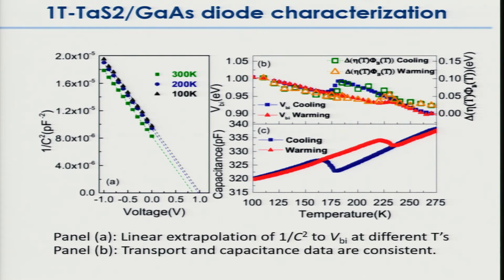And in panel B, the transport and capacitance data are consistent with each other. The open squares are the product of the ideality and the zero voltage barrier heights. Those are things we measure in forward bias, and we're taking the change in that product, and we know that that's essentially the change in the flat band voltage, if you want to look at it that way. But these data overlap each other. The data determined in forward bias overlaps the data determined in reverse bias. And the capacitance data is just measuring the capacitance itself, and it shows a capacitance increase here, which corresponds to a VBI decrease from that 1 over C squared equation I showed you, which is linearly proportional to VBI. So all the data are consistent, and the behavior in the resistance transition is replicated at the interface.